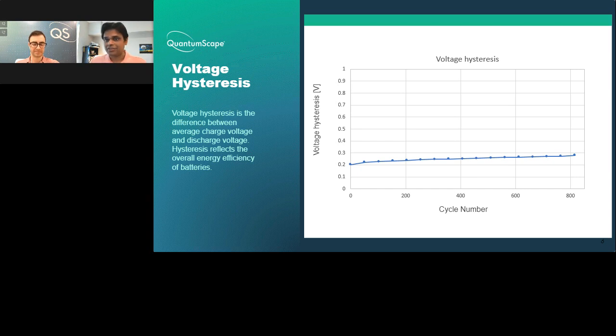So that means that the cell is extraordinarily efficient to begin with, and then it's of course staying efficient over the lifetime. This is comparable to some of the best lithium-ion cells. So this is, I think, pretty spectacular for a lithium metal cell, and well beyond the state of the art in terms of where other lithium metal cells are for this kind of charge discharge performance. The QuantumScape cells, the data that we see here, is much better than what any other lithium metal cell is capable of today.